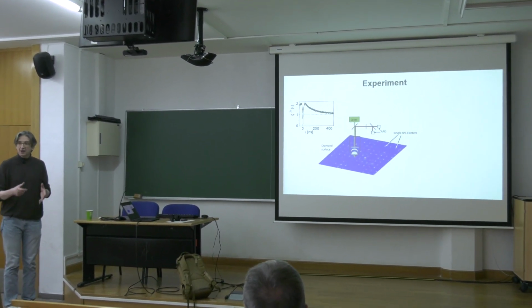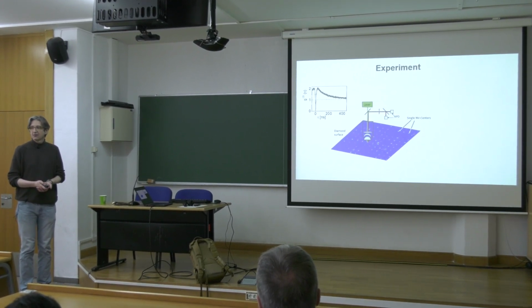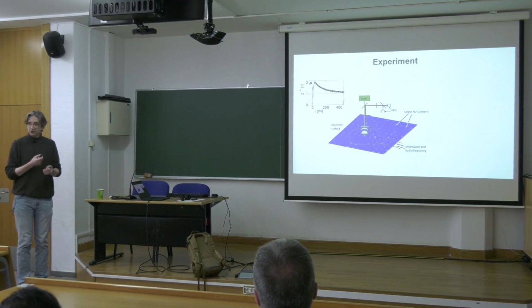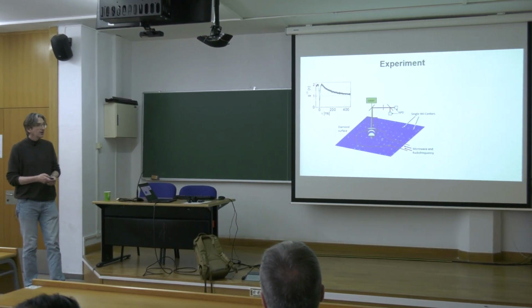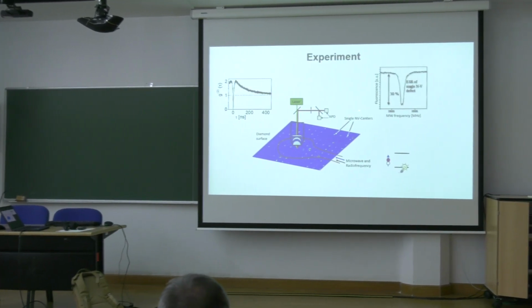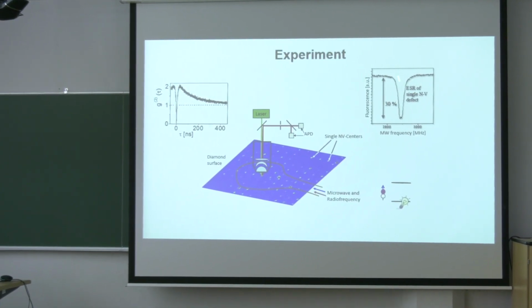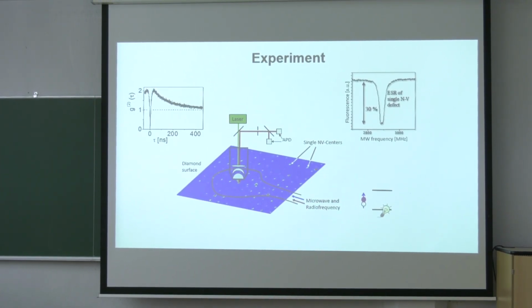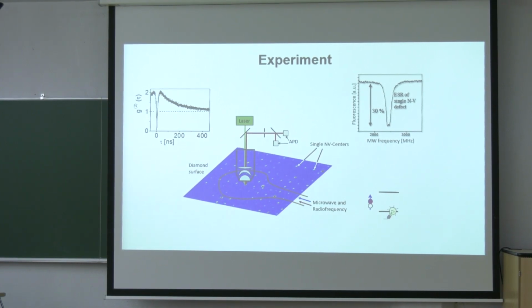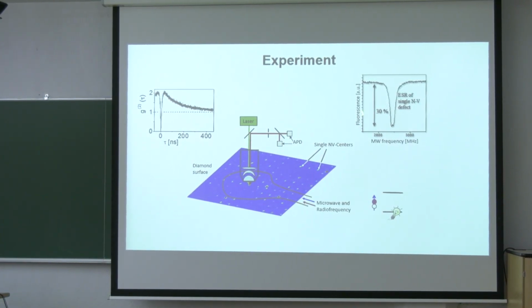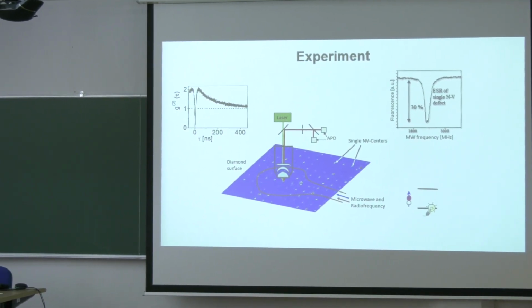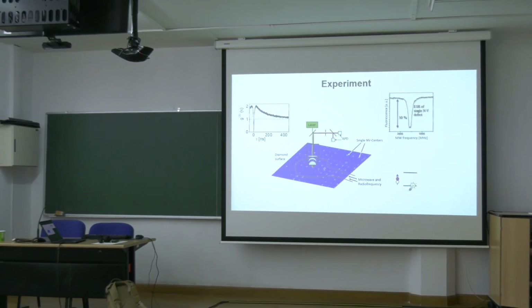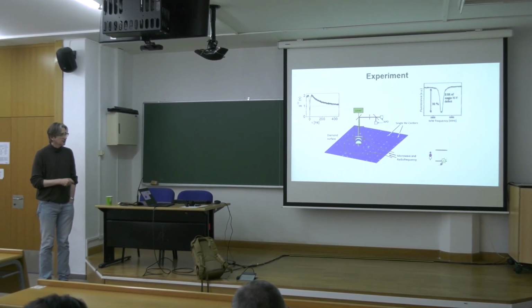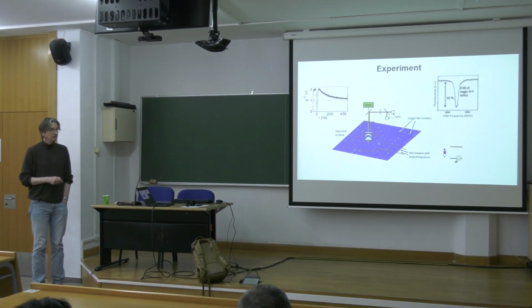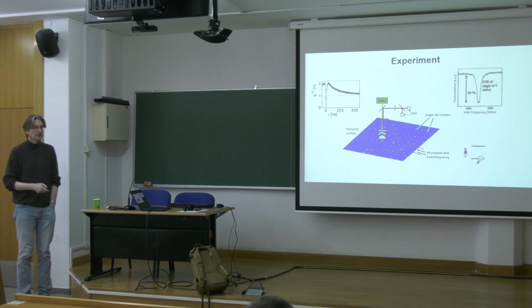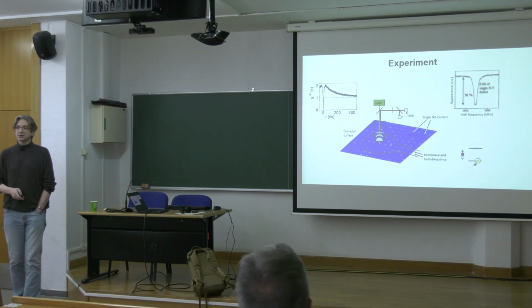In addition to the optical setup, which is a very conventional confocal microscope, we also apply microwave using a microwave antenna to control the spin state. Now by measuring the brightness of a single color center and sweeping the microwave through the resonance, we can observe spin flips if we hit the right transitions, and that leads to redistribution of population between different spin sublevels. Remember, they have different brightness, so you get a drop in fluorescence by 30% if you hit the spin transition. And these experiments can be done because it's optically detected on a single spin level. So you see that it's a single atom by measuring the g2 function, but you have quite a significant signal-to-noise ratio already after a few tens of seconds acquisition time on detecting the spin state of these color centers.